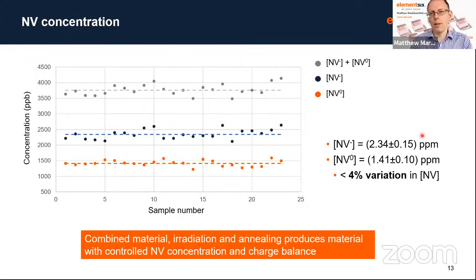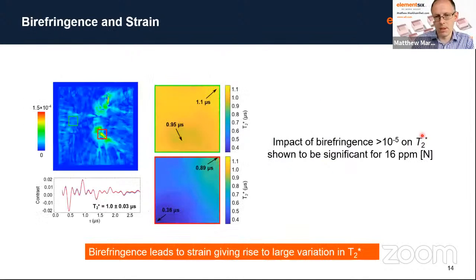Obviously, the key thing is what the spin properties of this material are. I mentioned earlier that strain is probably one of the key parameters, and we can see this in this plot. This is a birefringence image of the sample, and the coloration denotes a variation in that birefringence. Birefringence in diamond typically comes from dislocations in the material. In this particular sample, it's probably a dislocation bundle from the substrate, generating this high strain in the material. And what we can see in this plot here is data from Ron Walsworth's group at Maryland.